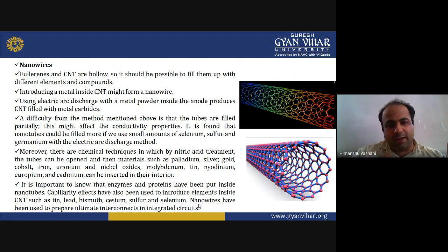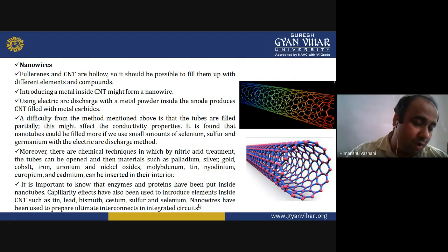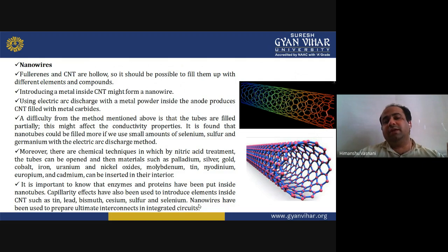A difficulty with the method mentioned above is that the tubes are filled only partially. This might affect the conductivity properties. So it is found that nanotubes could be filled more if we use small amounts of selenium, sulfur, and germanium with the electric arc discharge method.